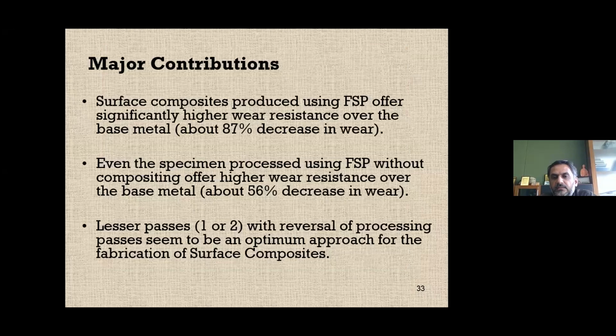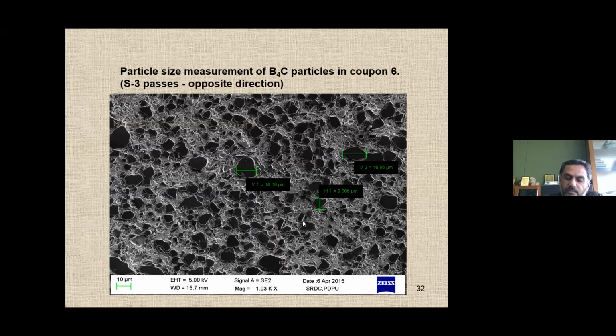And we found that 1 or 2 passes, and that too in reversing direction, help. Instead of applying all the stirring passes in the same direction, if you change the direction, this will help you get a better distribution. This is what you can see here: your reinforcement has been distributed more significantly rather than agglomerated. One of the limitations of the process is to avoid agglomeration. If the particles get agglomerated at one location, you will lose the property. So particles have to be distributed more uniformly. And how will you ensure more uniform distribution of the reinforcement? With the help of more FSP passes, either in the same direction or in the reverse direction.